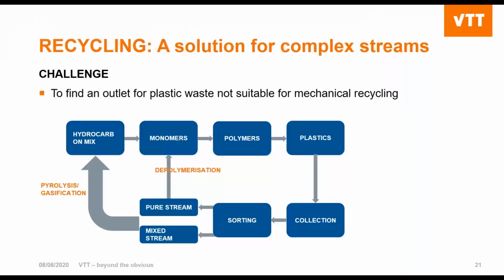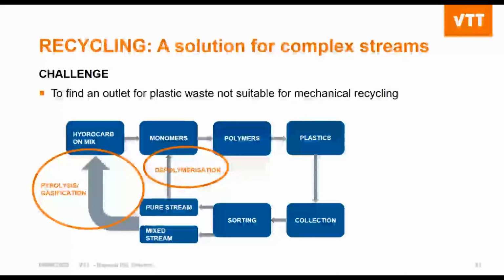There are many different chemical recycling technologies. They have all in common that the polymeric backbone of the plastic is destroyed. This can be achieved in different ways. We have here from relatively pure streams the possibility of a depolymerization. This is a relatively benign chemical recycling route, which gives us neat monomers. However, it's also limited to certain types of polymers with heteroatoms in the chain, for instance, polyesters or polyamides. Unfortunately, for the majority of plastics, this route is not applicable. For instance, polyolefins are better suited for thermochemical recycling technologies such as pyrolysis and gasification.